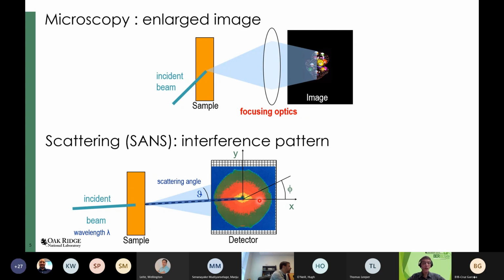In many cases of small angle scattering, we have isotropic patterns where all of this is circular. That's similar if you're familiar with powder diffraction, with the rings in the powder diffraction pattern. They're circular, and they're isotropic, and all of the information is just in this theta angle, so in the angle away from the beam. And that's what I will be focusing on today. So we usually call this then isotropic samples. And a good example is solution scattering. So if you have anything in dilute solution, there is usually no preferential orientation of scattering objects,